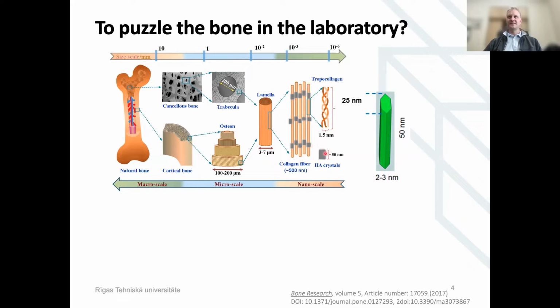And as we see here, which is quite well characterized, the crystals are a plate-like structure. So the crystals are about 50 nanometers in length, 2 to 3 nanometers thick, and 25 nanometers wide. And just in order for you to understand, the size of this crystal is about 1/10,000 of the diameter of the hair that you have on your head. So that means that the crystals are really, really, really small.